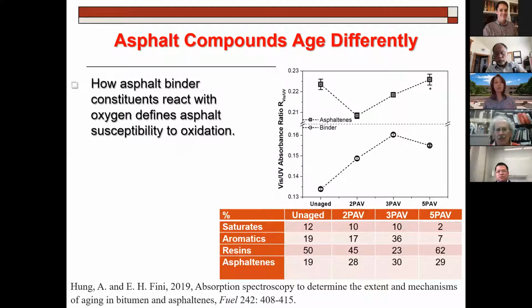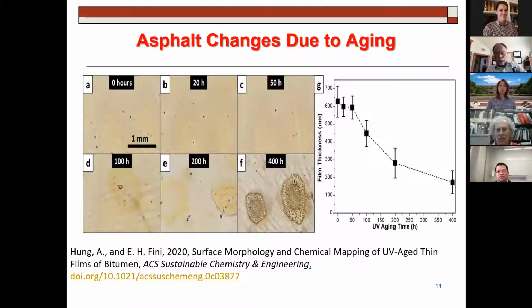Just keep that in mind. So I want to show you this one as well, that you may think of aging as oxidation. Yes, that's the dominant effect of aging, but it's not the only thing. I'm showing you this figure to show how from 0-hour aging to 400 hours of aging, the shape or surface of the material changes under optical microscopy. It looked like this, and after 400, it looks like this. So the shape is changing.